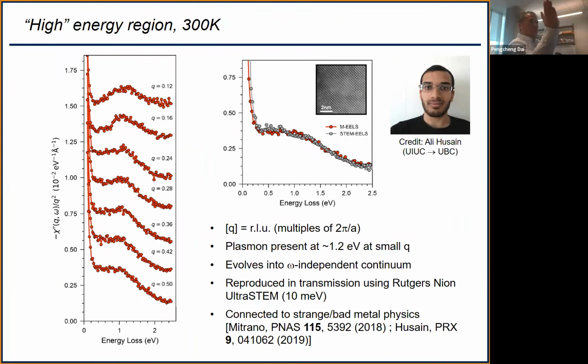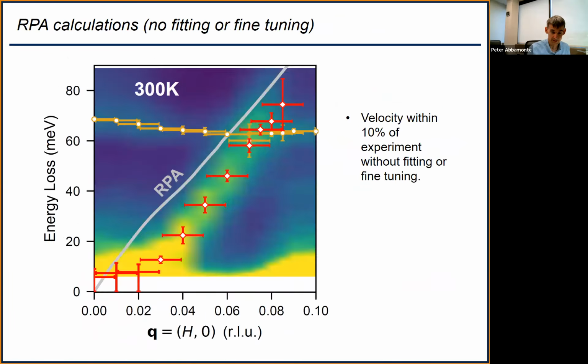Oh, you just rotate the sample, right? With respect to the beam. We rotate the sample and the analyzer in conjunction to keep Q perp fixed and change Q parallel. So it changes when you rotate the crystal, and that's how we get the dispersion. I think a better question is, if we rotate the direction of Q in the plane, does it change? And it does.